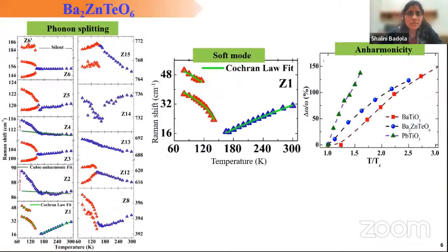To address this, we have carried out temperature dependent Raman spectroscopy on BZT, where we found that most of the phonons split below the phase transition, that is below 150 Kelvin. Particularly if we look at this lowest frequency phonon mode, that is Z1, it first exhibits an anomalous behavior upon cooling, and below 150 Kelvin, it shows normal behavior.